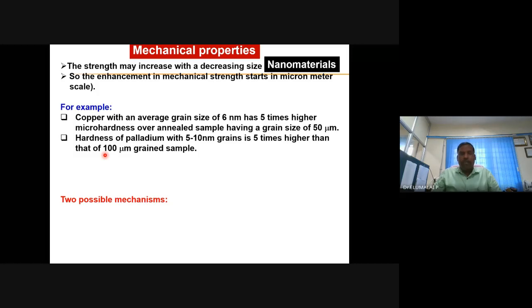There is a saying, and there is a witness also, not only saying: carbon nanotubes have much higher strength compared to steel. You see here, copper with 6 nanometer particles has 5 times higher hardness compared to bulk copper. Palladium consisting of 5 to 10 nanometer grains has 5 times higher hardness than bulk material. Mechanical strength increases at the nanoscale, not necessarily only for carbon, for other materials also.